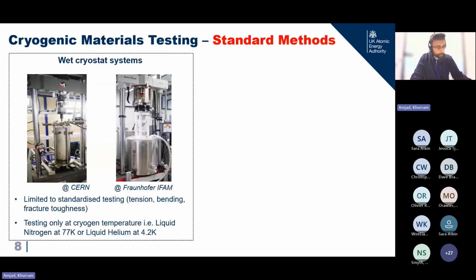Okay, before I jump into our rigs, I'd like to provide a brief overview of the standard methods for testing. Historically, when we talk about low temperature testing, we talk about liquid filled dewars which are fitted onto the load trains. In these traditional setups, the testing is limited to cryogen temperature. So for nitrogen, 77 Kelvin, and for liquid helium, it's 4.2 Kelvin. And if we somehow do it for liquid hydrogen, that would be at 20 Kelvin.